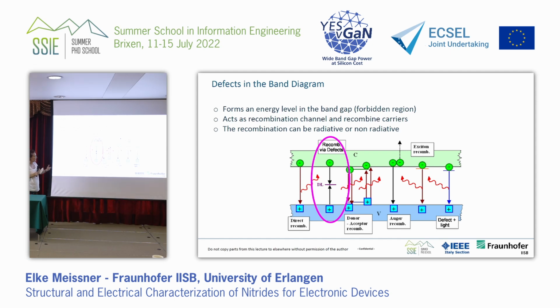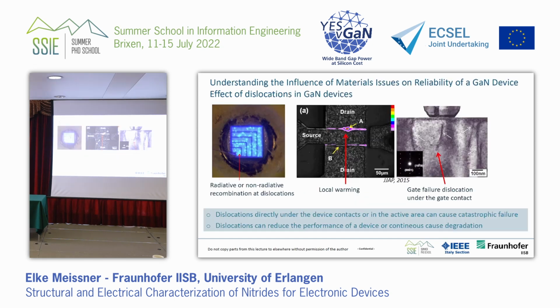Why is it difficult for a device, such a dislocation? Because the dislocation creates levels in the band gap. And this is what we're talking about, recombination action. So a dislocation can be radiative, non-radiative, create, let's say, recombination channels over defect levels between the conduction band and the valence band. And this is the problem that we don't like. And here are some examples how we measured it in a device.